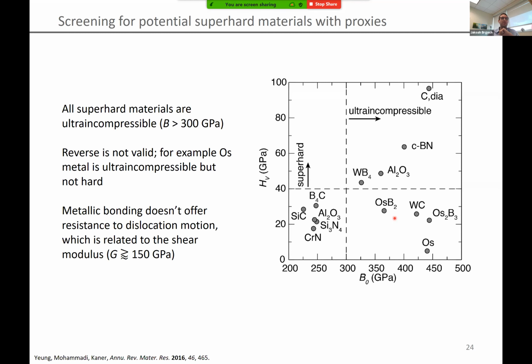But if you take something like boron and add in these covalently bonded elements from the main group, you begin to add a scaffold that holds the osmium atoms in place. So now if the osmium metallic atoms want to start moving around, they can still move somewhat, but they start to bump into these covalently bonded scaffolds that are not going to move.